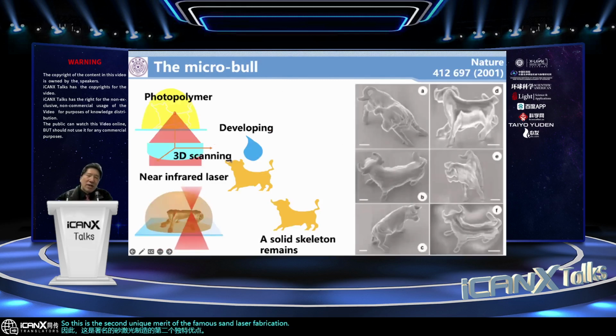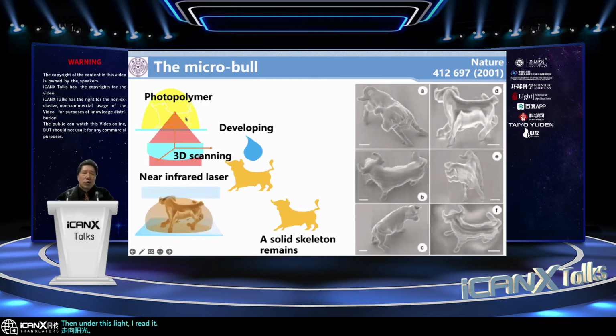Now I give you one example of how we use the femtosecond laser to do 3D fabrication. Here is an optical glue. Generally, we paste the glue to the cover glass. Then we shine the glass to the sunshine. Under this light irradiation, a chemical reaction occurs. Actually, this photopolymer's original status is liquid. They consist of small molecules. But once they are excited by the sunshine, by light, and the chemical reaction occurs, the small molecules become